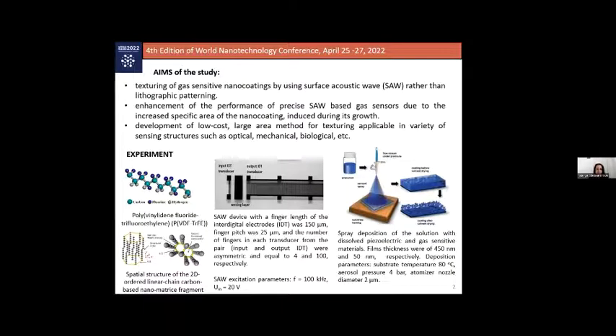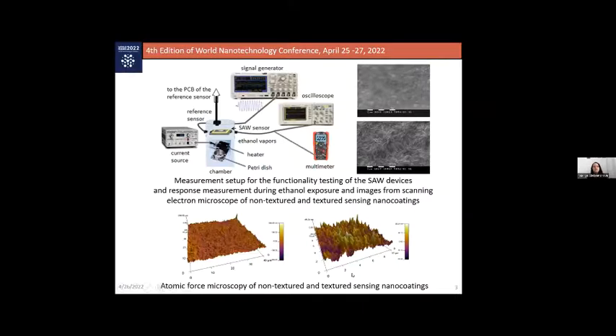One of the samples was a control sample without any acoustic wave excitation during the growth. The other one, for comparison, was excited with the following excitation parameters: high frequency and high voltage. And the test of the two sensors was in a conventional chamber for electrical characterization of sensing properties, including controllable release of precisely controlled concentration of ethanol at every moment, with a reference sensor for calibration.